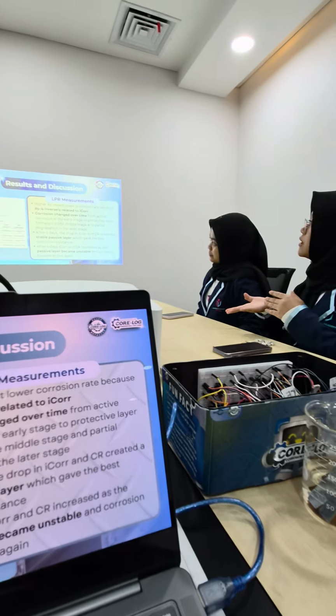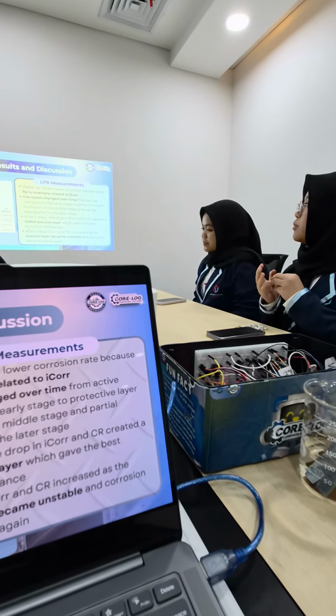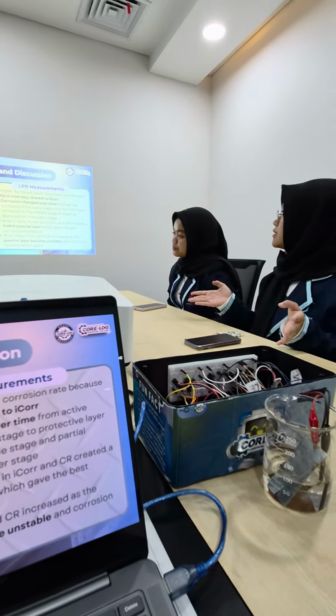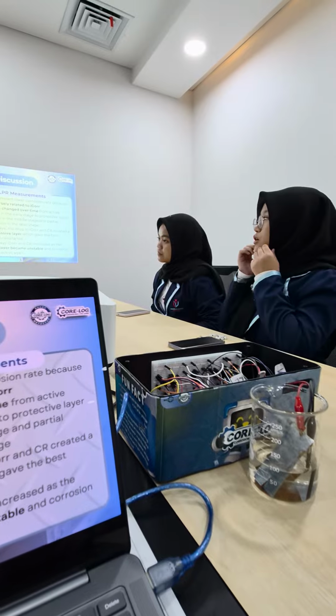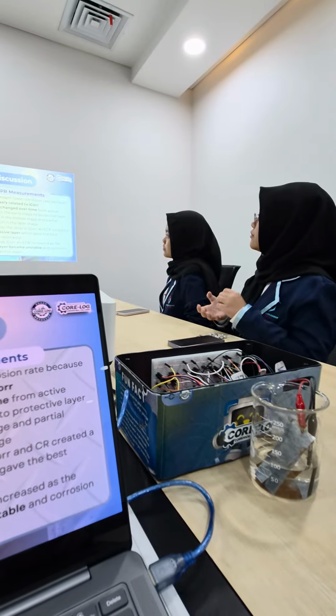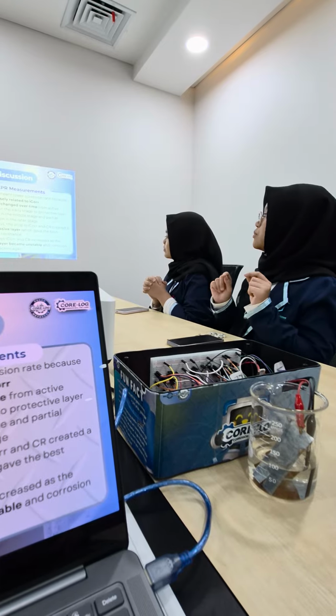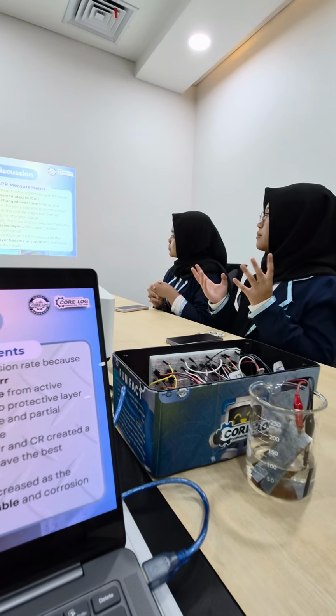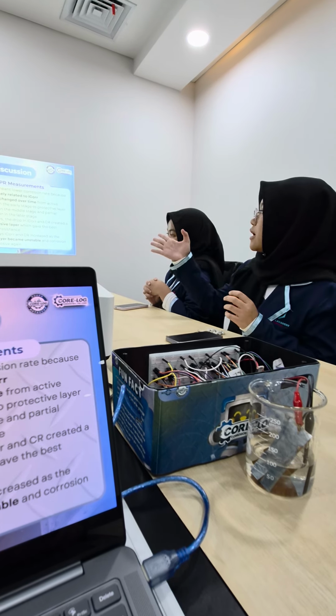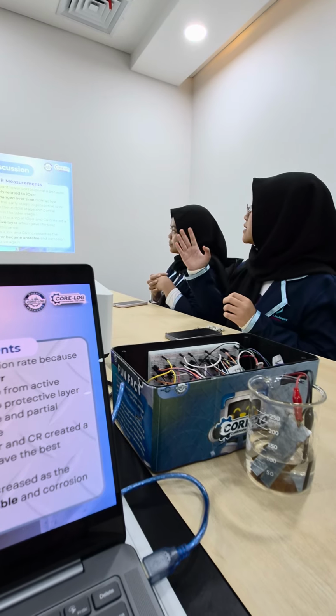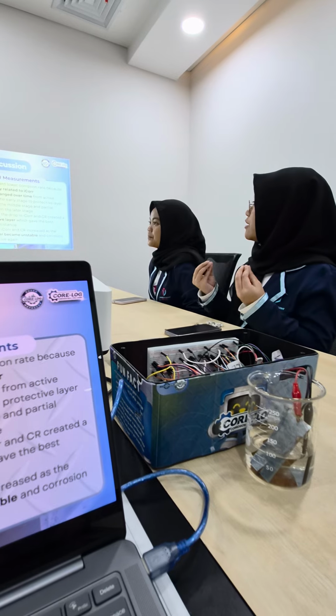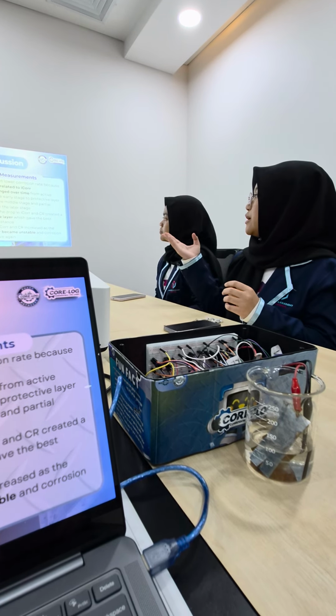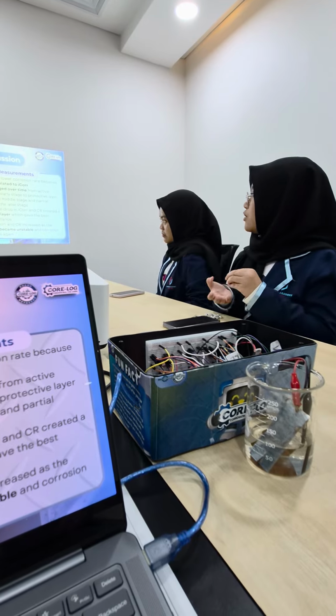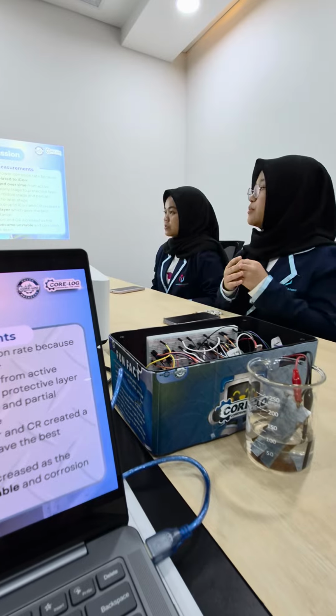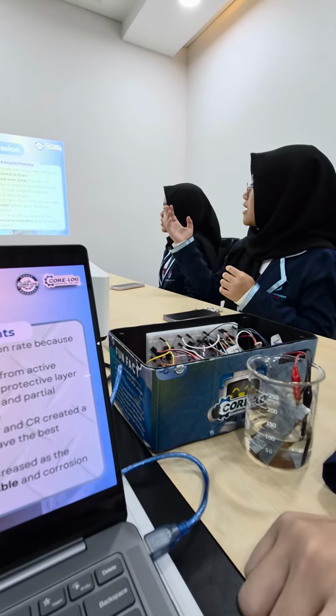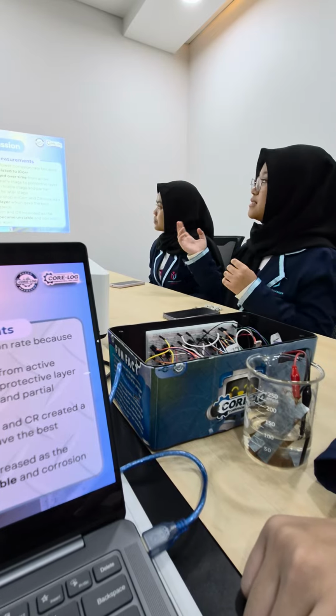As we can see, in all measurements, the higher RP or polarization resistance means a lower corrosion rate, because RP is inversely related to I-corr or corrosion current. And we can see that corrosion changed over time from active corrosion in the early stage to protective layer formation in the middle stage and partial degradation in the later stage. After 2 days, the drop in I-corr and corrosion rate created a stable passive layer, which gave the best corrosion resistance, while the RP increased. And after 4 days, the I-corr and the corrosion rate increased as the passive layer became unstable and corrosion became active again. As we can see, the RP decreased.